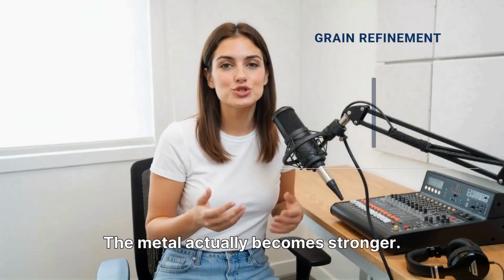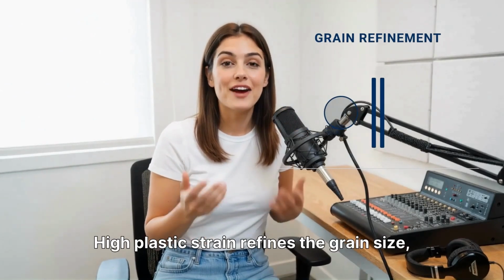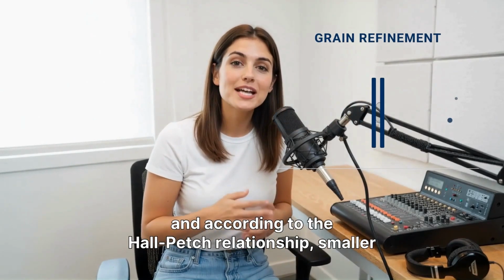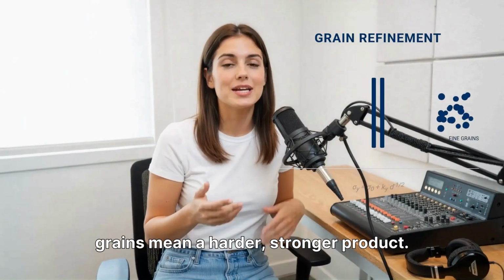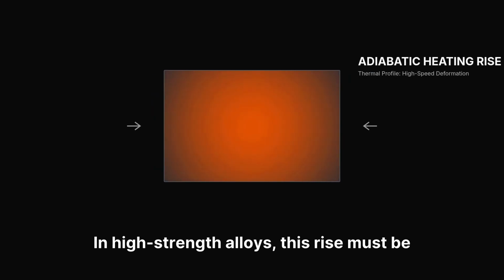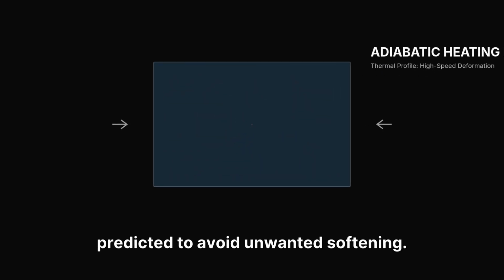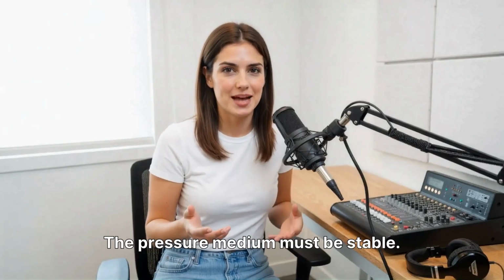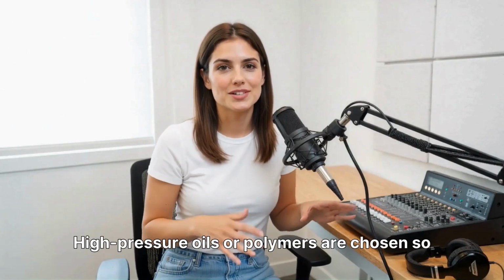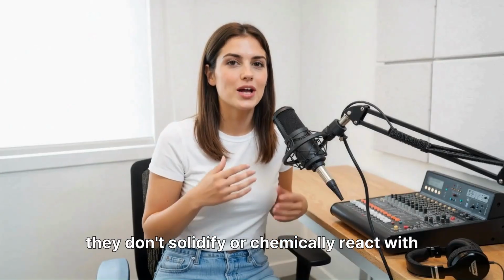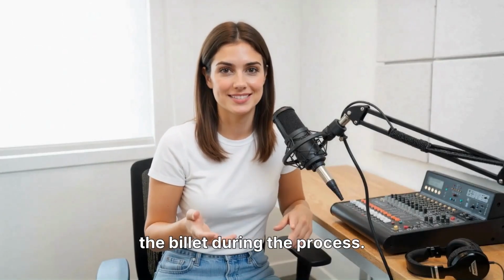The metal actually becomes stronger. High plastic strain refines the grain size, and according to the Hall-Petch relationship, smaller grains mean a harder, stronger product. We must manage adiabatic heating. Mechanical work converts to heat instantly. In high-strength alloys, this rise must be predicted to avoid unwanted softening. The pressure medium must be stable. High-pressure oils or polymers are chosen so they don't solidify or chemically react with the billet during the process.